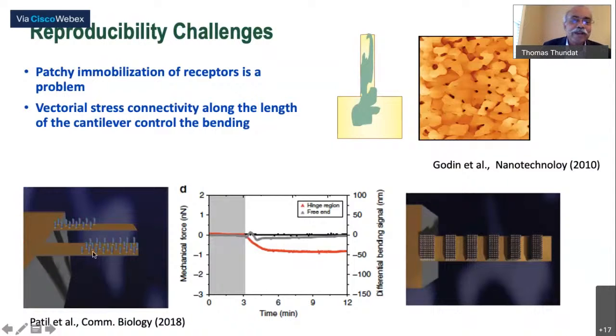So we found out that as long as they are vectorially connected, that means if the modification is like this, there is no change in bending. But if we make it only towards the end, you can see that it bent a lot. And if it is very much towards the end, it doesn't happen. So I think I'm running out of time, so I will basically go a little faster.